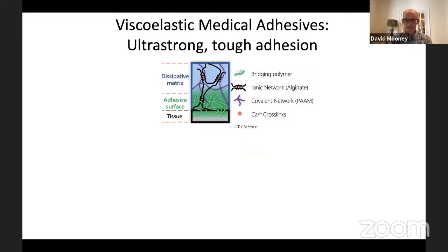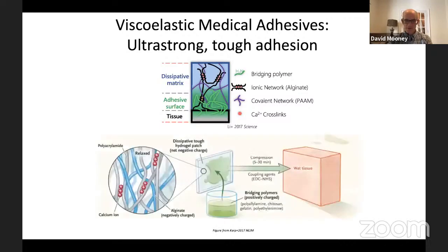They specifically proposed to use chitosan that could form entanglements, ionic interactions, and also covalent linkages between the two. The basic idea is we'd have our gel, we'd coat it with a chitosan solution, place it in contact with the tissue for a short period of time, allow adhesion to occur, and now have a material that would conform to the underlying tissue, be capable of dissipating significant stresses as it moved and flexed in response to loading from the tissue itself.